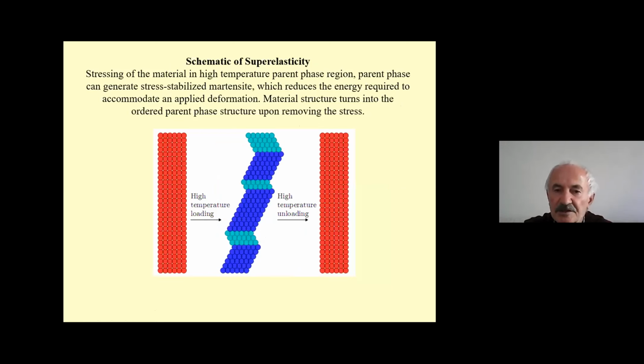This is a schematic of superelasticity. As I mentioned, in superelasticity the material is stressed in the parent phase region, and ordered parent phase structures turn into detwinned martensitic structures by means of stress-induced martensitic transformation. Upon releasing, the detwinned structures turn into the ordered parent phase structure by means of reverse austenitic transformation.